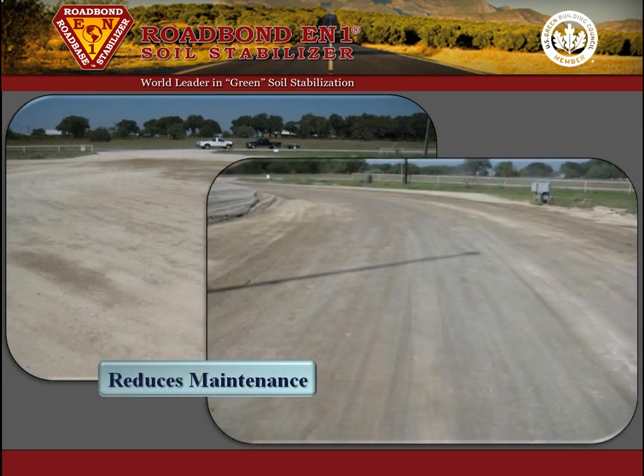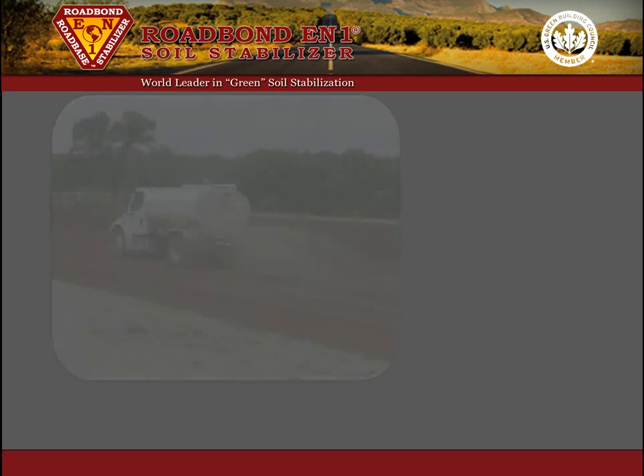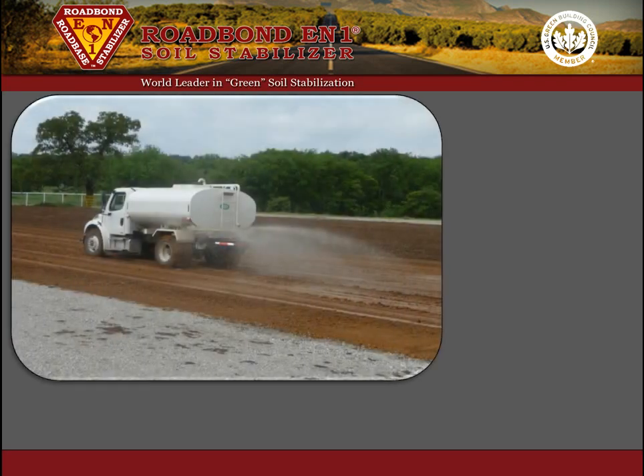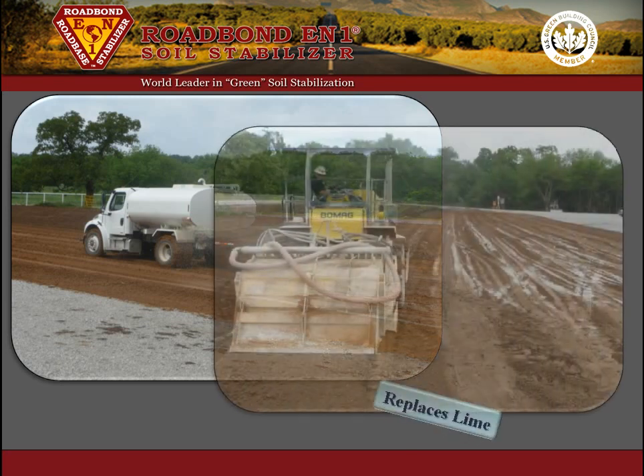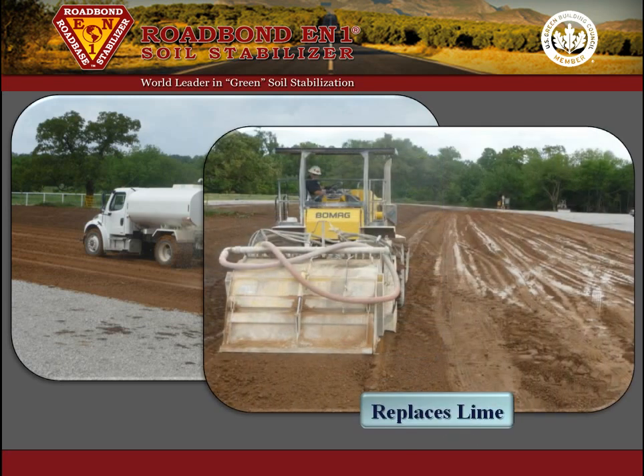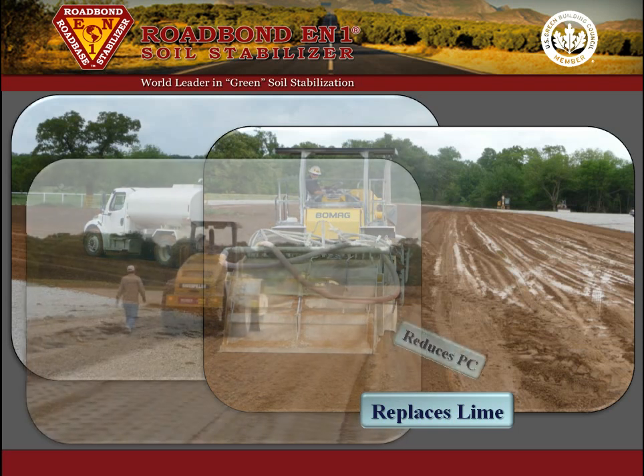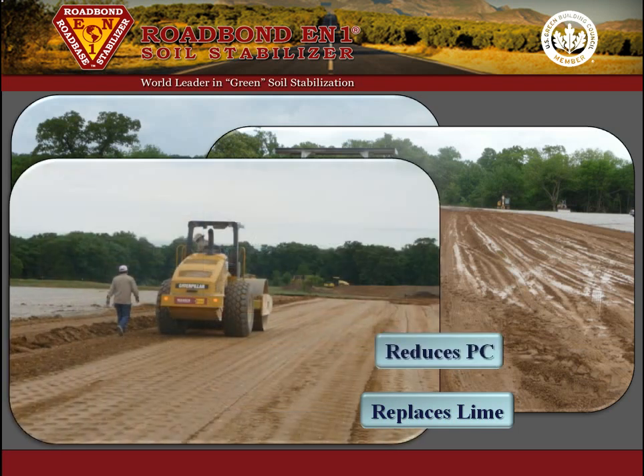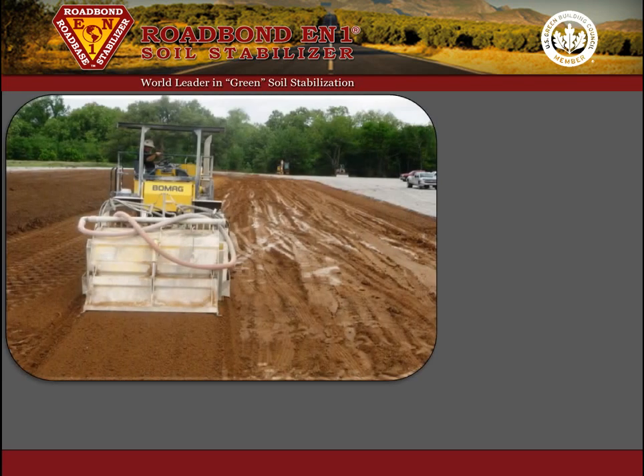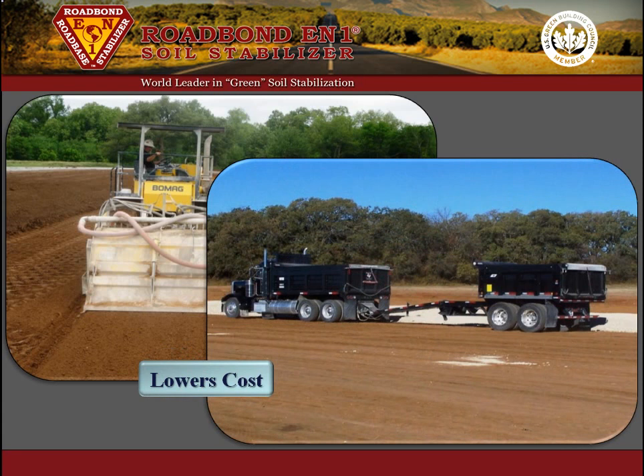A typical location and Lease road is firm and dry after months of traffic and will require less maintenance over time. In the Woodford Shale in Oklahoma, XTO Energy has adopted the use of Roadbond EN1 on its drilling locations and Lease roads. Lime stabilization has been eliminated completely, and the use of Portland cement has been dramatically reduced. This method saves construction time, reduces truck traffic to and from the location, and has lowered the total cost of the stabilization by over 50%.